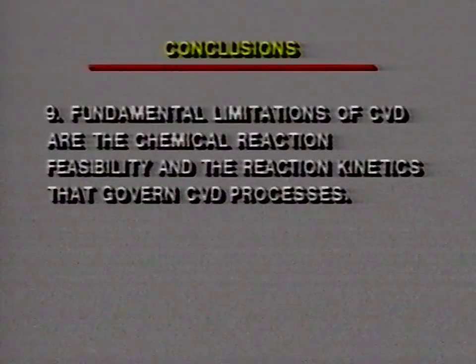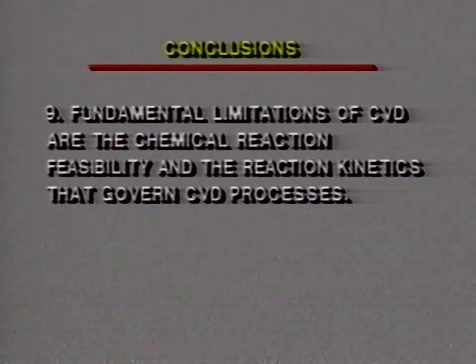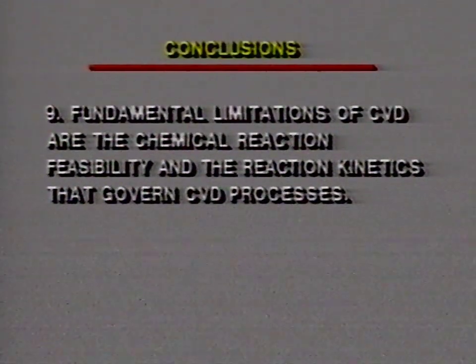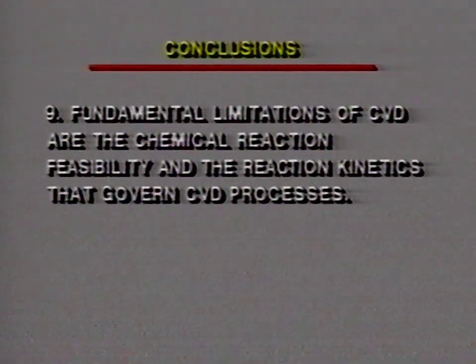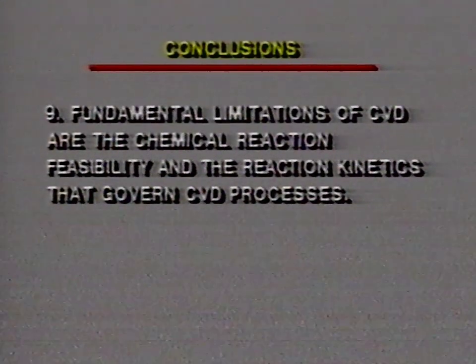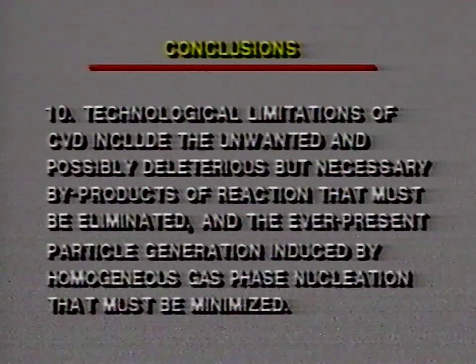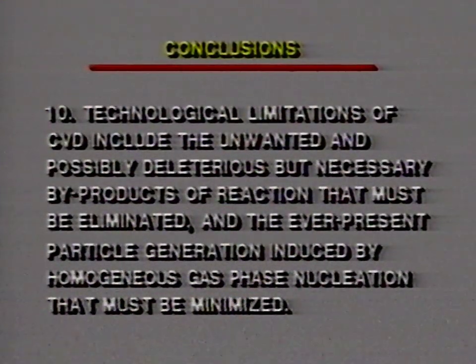As far as limitations are concerned, the fundamental limitations of CVD are essentially the reaction feasibility and the reaction kinetics that govern the CVD processes, and that's really about as fundamental as you can consider it. The technical limitations, on the other hand, are shown here. They include unwanted and possibly deleterious but necessary side products which are always present. And of course the ever-present particle generation, as I mentioned already, by the homogeneous gas phase reaction that must be minimized. So those are perhaps the limitations that have to be eliminated or at least solved to a better extent than we are now capable of doing.